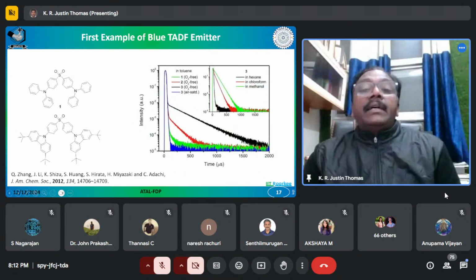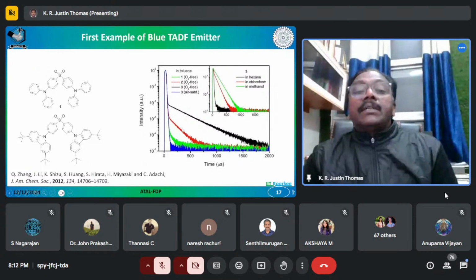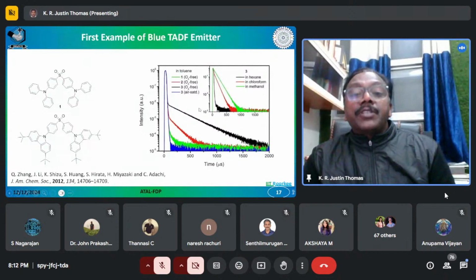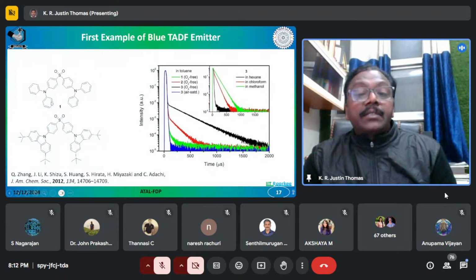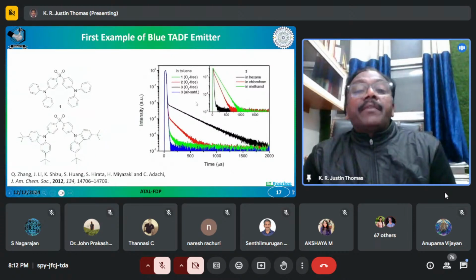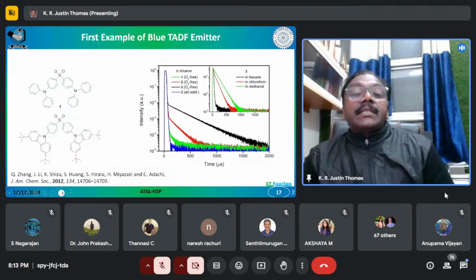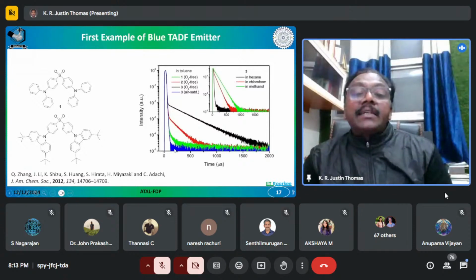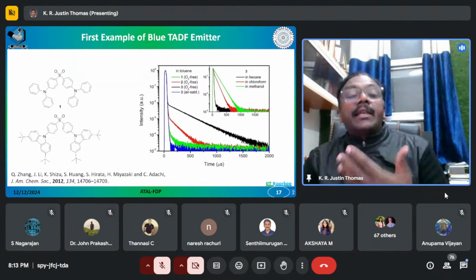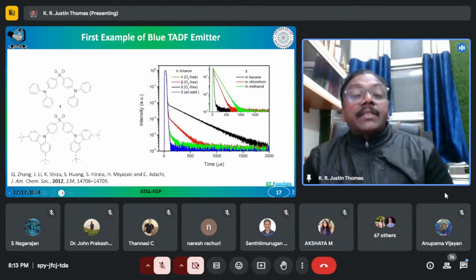So you can see here, when you measure the lifetime for compound 1, this compound 1 shows only one type of fluorescence. See, there is no delayed component. However, when you go to compound 3, here you have a very good delayed fluorescence. That means this one is showing TADF, but the other is not, or even if it is, it is very weak. And at the same time, you can also see that with oxygen, shown here as a blue trace, oxygen is found to quench the triplet excited state. So a single exponential decay is observed for the molecule in oxygen. That means it is completely quenching the delayed fluorescence here. Okay, that is also proof that it has TADF.